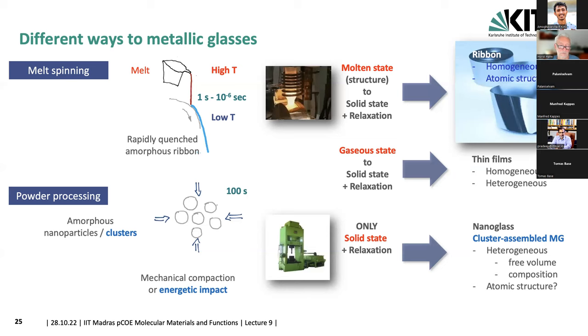But the idea, which originally came from Herbert Gleiter, in the 80s even, he tried this in one experiment. He said, what happens if we take amorphous nanoparticles of, let's say, 10, 20 nanometer, and we compact them, would we still get a homogeneous structure, or do we get something else? And it turns out we get something else. We get a nanoglass, which has now, between these particles, which you see here on the left side, an interfacial region, which has been found to consist of a different amorphous structure.